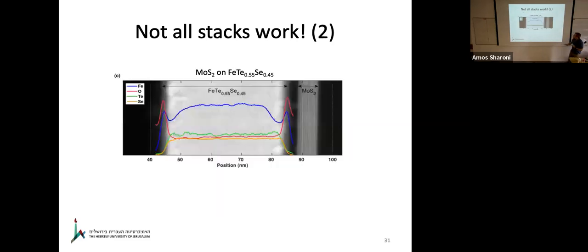pretty. Another example, which is another painful example: we tried to build a device with MoS2 on top of iron selenium telluride. It's claimed to be a topological superconductor. What we get is a very ugly oxide, magnetite, here at the interface, a gap, and here is the tunnel barrier. Once again, that means that it's very, very hard to build a tunnel device this way.